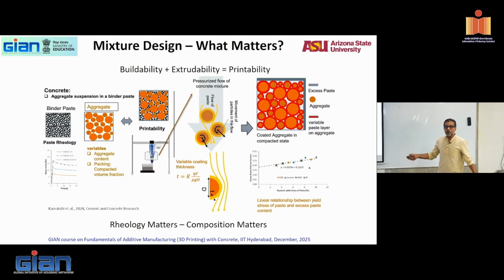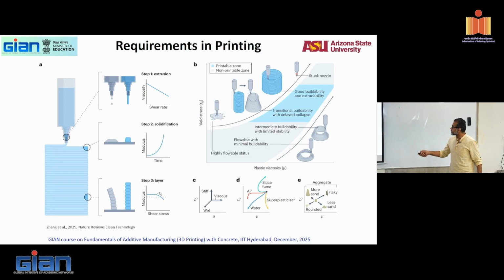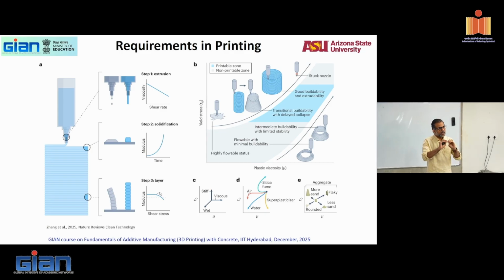Silica fume. Now you add silica fume, what happens? Why am I doing this? When you add silica fume, what happens? For a certain dosage, you might see viscosity dropping a little bit, right? You will see the flow becoming easier because silica fume particles accelerate the flow at a very low dose of 1%, 2%. But when you get to 3, 4, 5%, they have the opposite effect. They start to collect all these particles together, start to clump. You will need more admixture. So depending on what you want with yield stress, you can play around with silica fume.